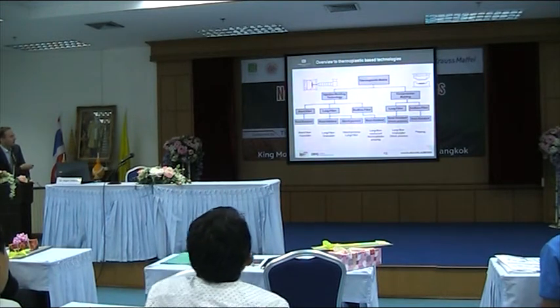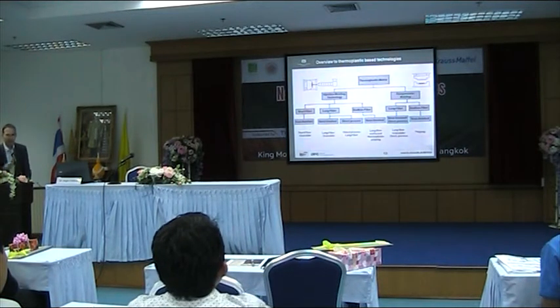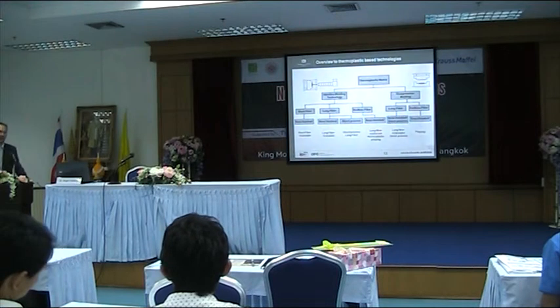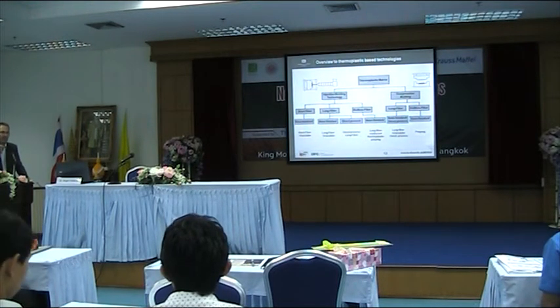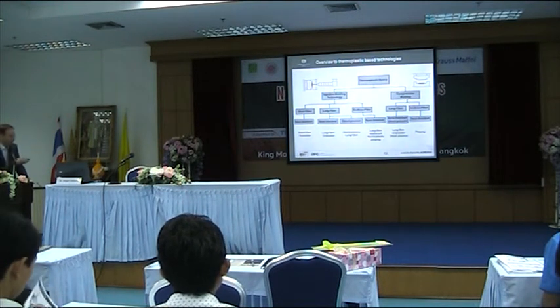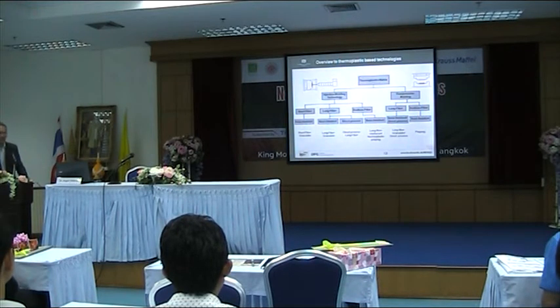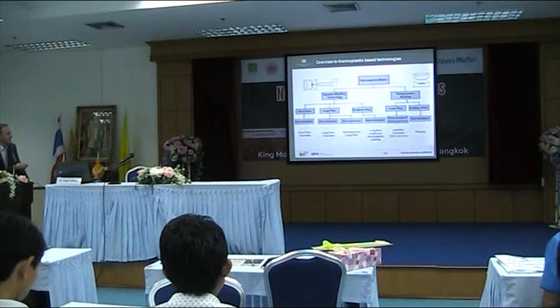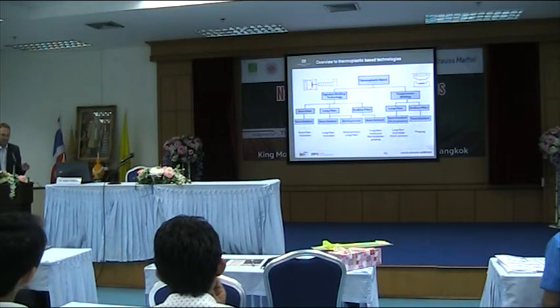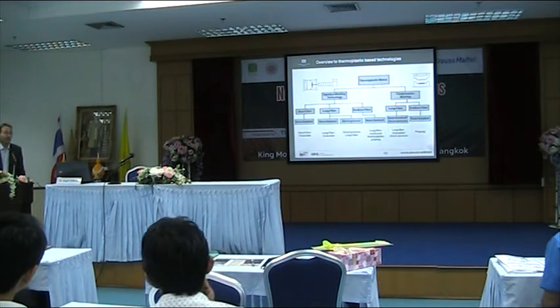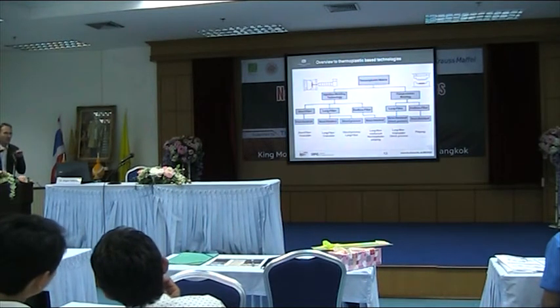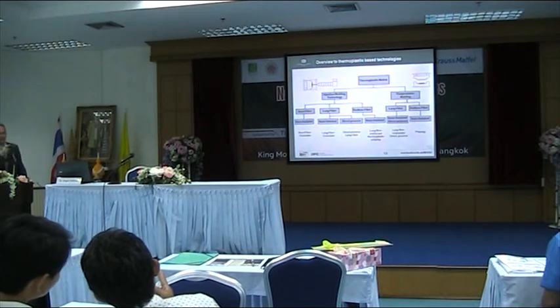So for both injection molding and compression molding, you can use short fiber, which is a definition. We say short fiber is something with a fiber length, always looked at relative to the part, below 1 millimeter. Something between 1 millimeter and 10 millimeters is treated differently in the literature and in the state of the art. This is what we call long fiber. And then we have endless fiber. We call all parts endless fiber where the fiber length is similar to the dimensions of the part. So if you have a typically shaped plain part, the fibers should go from one end to the other end.